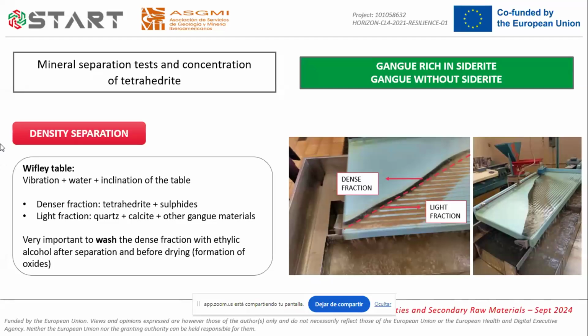It is very important also to wash the dense fraction with ethylic alcohol after the separation and before drying this concentrate in order to avoid the formation of oxides. Here in the photographs, we can see very easily how the minerals are separated because there is a big difference of color between the dense fraction and the light fraction.